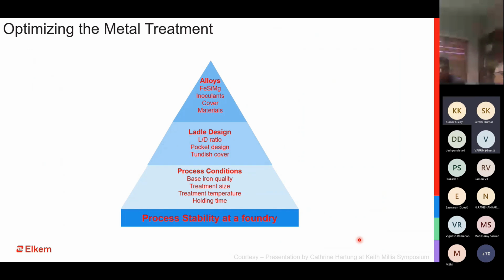But does a good inoculation ensure that you get a very good casting? Or does it alone ensure it? Definitely it helps, but it is not just the metal treatment or the inoculant. This is more of a disclaimer from the inoculant manufacturer, that it is not just the inoculant which ensures that you get a very good casting. It's more towards the process stability. It's more towards the process conditions like the base iron, the treatment size, the treatment temperatures, the holding time, the design of the ladle, and eventually the treatment alloys that make sure that you get a much better process stability, you get a much better casting.